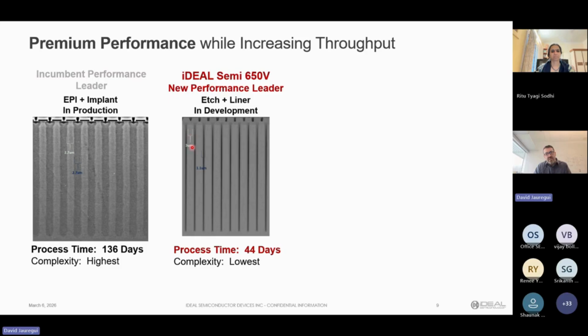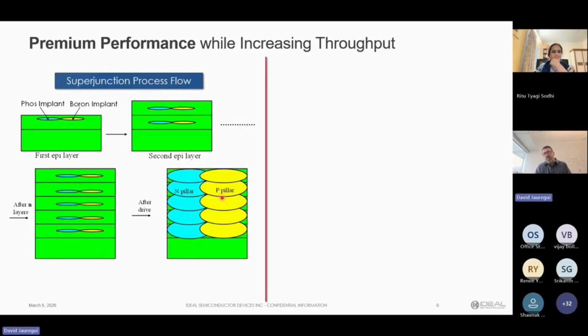More importantly, you can see this is our mesa here. The darker gray lines are the charge compensation. This structure shows a 1 micron mesa with a 1.1 micron trench. This was our first prototype. Actually, the 650 volt MOSFET we'll be releasing today is going to increase this to 4 microns with a 1 micron trench, meaning that we will be utilizing about 80% of the conduction area, versus this structure here, which is only utilizing 50% of the conduction area. So that's one deficiency. But then this gets into the manufacturability of how to build that traditional super junction structure.